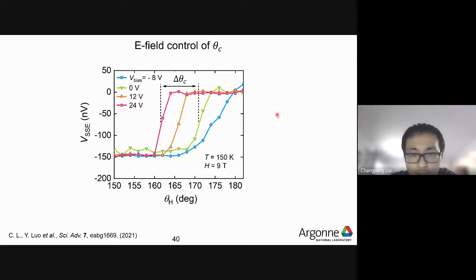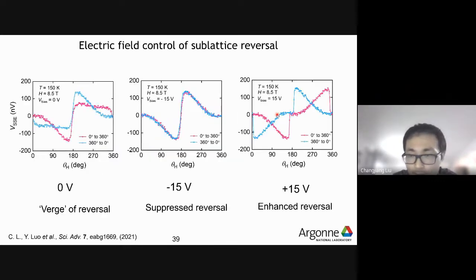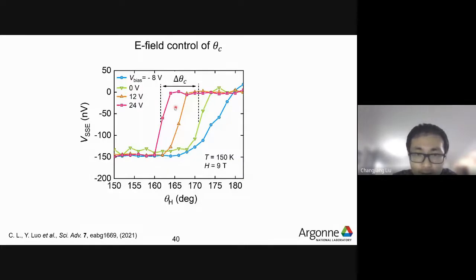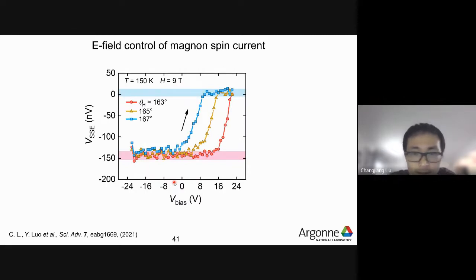So we further did the measurement near the spin flop transition. We found that the transition angle can be tuned by applying a gate voltage. You see, from negative 8 volt to positive 24 volt, the transition angle can be tuned by more than 10 degrees. The x-axis is the angle of the magnetic field. So this means we could do the measurement at a fixed field angle while simply applying a gate voltage, and this gate voltage could be used to induce the magnon transition in the spin Seebeck voltage directly. So this is indeed the case.